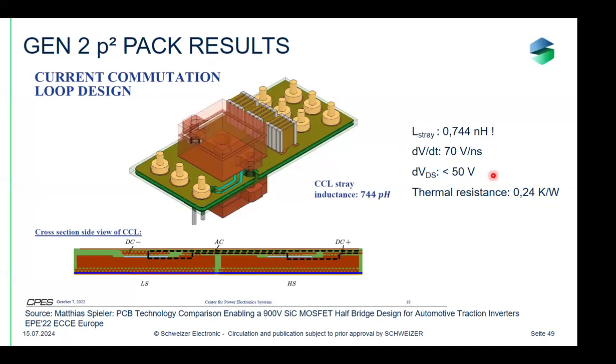So the publication of Matthias Spieler was "PCB technology comparison enabling a 900 volt silicon carbide half bridge for 800 volt applications." So today, if you look at 800 volt applications, typically 1200 volt components are used due to the overshoot voltage during switching. And with this publication, Matthias proved that you could also use 900-volt components for 800 volts. And 900-volt components have a lower RDS(on) than 1200-volt components. And this would be a benefit to even reduce the conduction losses, not only the switching losses. So this was a nice publication.